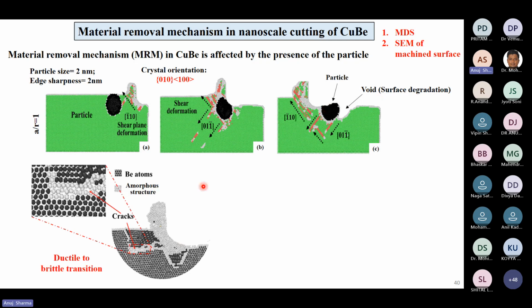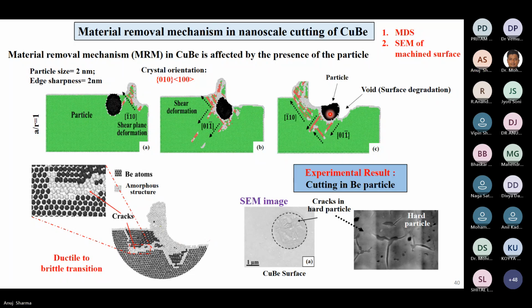And when the particle was closely monitored using MD simulations, it was seen that since it is hard and brittle in nature, there was some crack formation that took place in the particle. So these amorphous cracks were generated. This is shown by the amorphous layer. These are beryllium atoms, the black ones, and this shows the cracks which are separated by this white colored amorphous layer of atoms, which shows that there is a brittle transition taking place in the particle, a brittle fracture. And it was also observed in the experiments that when the surface was analyzed on these beryllium particles, there were cracks.